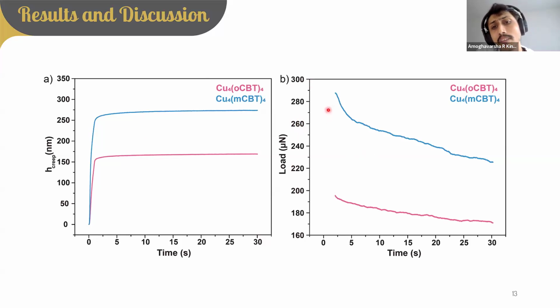Now coming to the stress relaxation curve, here we observe the changes in load after indenting the sample in 1 second. For up to 30 seconds, we observe the changes in load. We can see that the load keeps decreasing with time, indicating that under constant load, my material is slowly relieving the stress which is falling upon it. So my material is stable under constant stress, and it is also relieving the stress which is falling upon it. So this is a good material to use as a structural component for certain precision measuring instruments or some mechanical instruments, and also some crystal optics, etc.